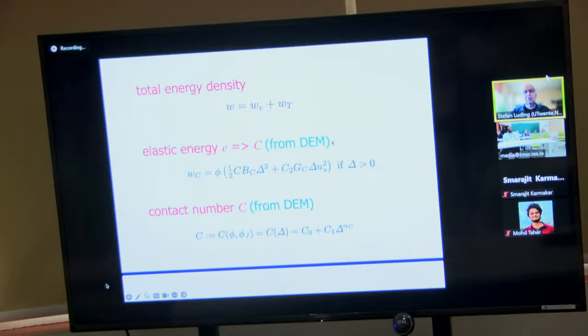Good. Okay, so I start from the very, very basics, and that is the total energy density. So the total energy density has an elastic contribution and a thermal contribution, which corresponds to the classical thermal or to the granular thermal, and then it corresponds to kinetic energy. So we have 2. The elastic energy we can deduce from particle simulations. DEM stands for discrete element method, and it is one method to simulate particles.